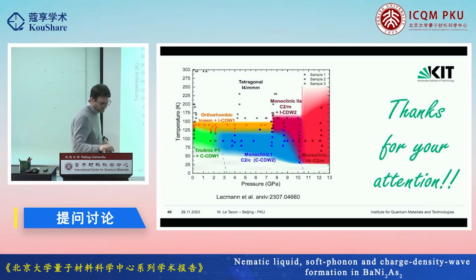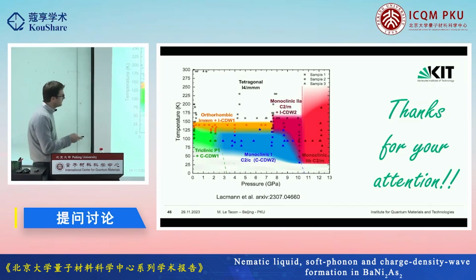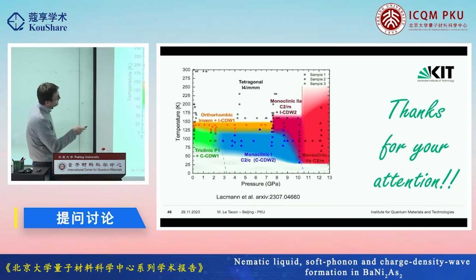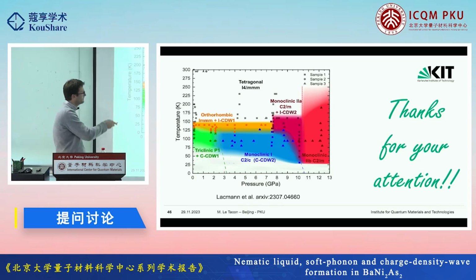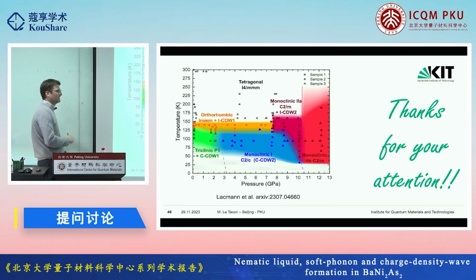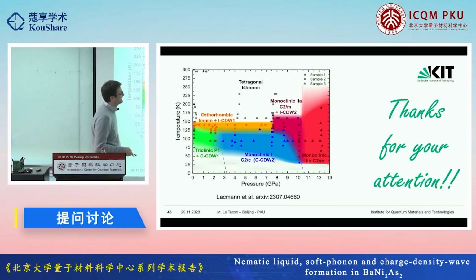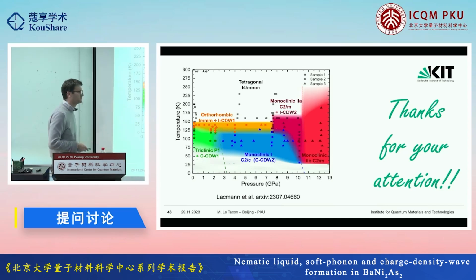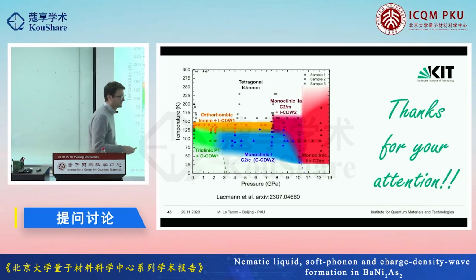That one is completely weird, a completely different incommensurate modulation. We don't have so much here about the temperature dependence. We plotted it this way, but we know that it's still there. I cannot tell you much about the onset or the offset here. We just have this point here with the temperature dependence. When you play with a diamond anvil cell in this temperature and pressure range, these are two or three beam times together. Unfortunately, you cannot explore this map as you would like because the pressure is sometimes a bit complicated to control. So I cannot really say here what's going on.